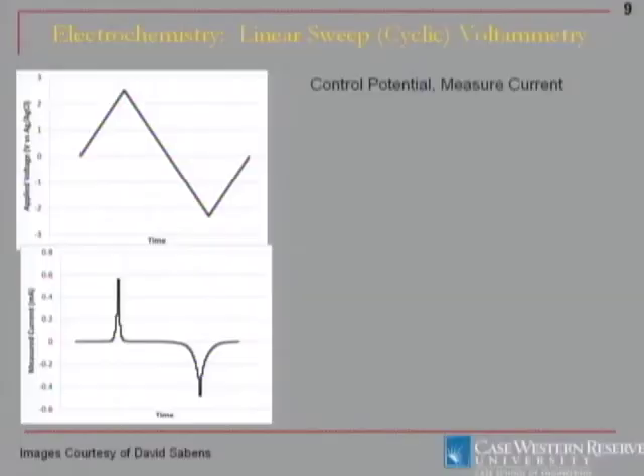One of the methods that's widely used is linear sweep voltammetry, where you control the potential and measure the current. This is what it would look like over time, sweeping the potential between two limits over and over again, and you monitor the current, which is associated with the various capacitive and Faradaic reactions occurring at the electrode. This, in this case, is the breakdown of water at the limit of your potential window. And this current is proportional to the concentration of species that have undergone charge transfer.